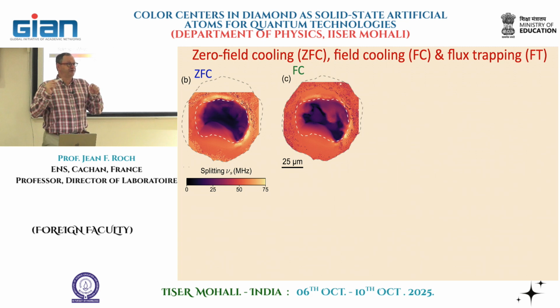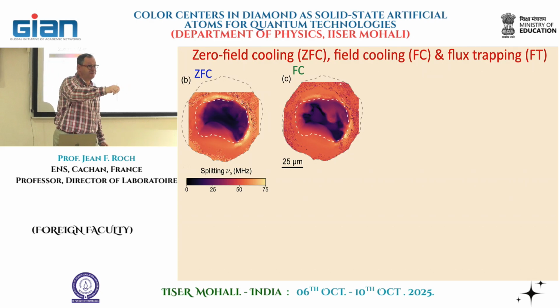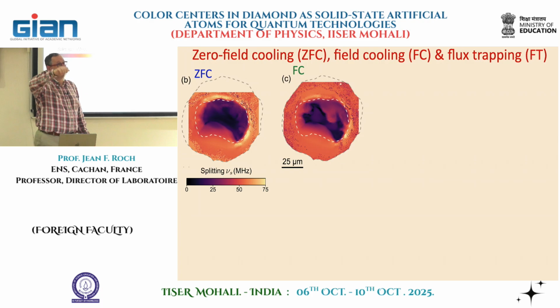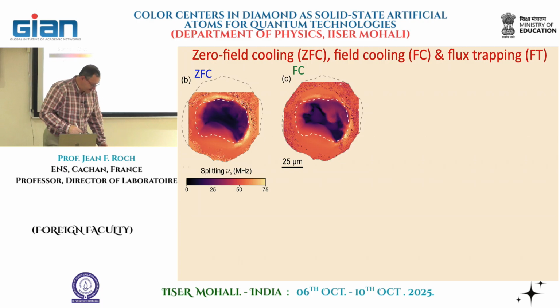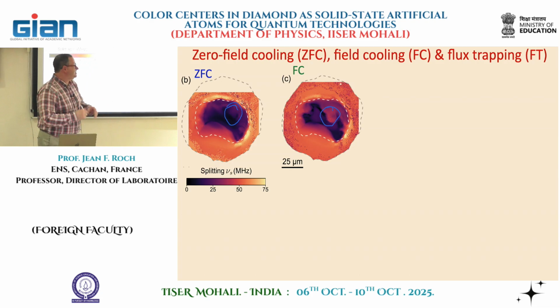Okay? Now, the field cooling regime is different. You start from a non-superconducting state at a temperature above the critical temperature. You already apply the magnetic field, and you cool it down. So somehow the system will keep the memory of the magnetic field, and then with the magnetic field on, you increase the temperature again. In that case, you see slight differences if we compare, for instance, this zone. We see that the two regimes do not provide the same information.